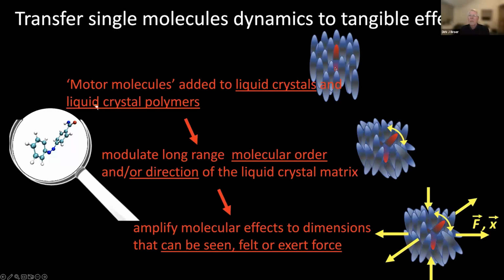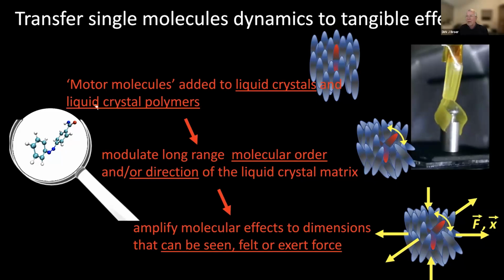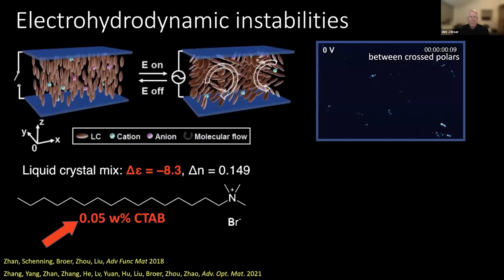You have a motor molecule embedded in the liquid crystal. You start changing the conformation, for instance. By changing the conformation, you change the order, and then the material might expand in one direction and shrink in the other direction. And by doing this, you can, for instance, create materials, as you can see here on this little movie, which is a material capable of lifting a weight.